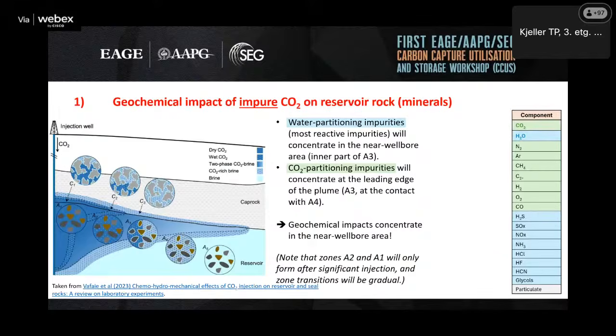When we have impurities in the CO2, they can be identified as either water partitioning or CO2 partitioning, and that will have a very big impact on where they go in the system. So when the CO2 spreads through the reservoir, the CO2 partitioning impurities will travel with it, whilst the water partitioning impurities will partition into any water phases. So when you have some water trapped in pores or on surfaces, that's where these impurities will go. And as you can see in my list on the right, that's especially the SOx, the NOx. So the acid forming impurities will typically stay close to the wellbore, close to the injection site, and not spread far into the reservoir. But that also means that their impact will be concentrated there.